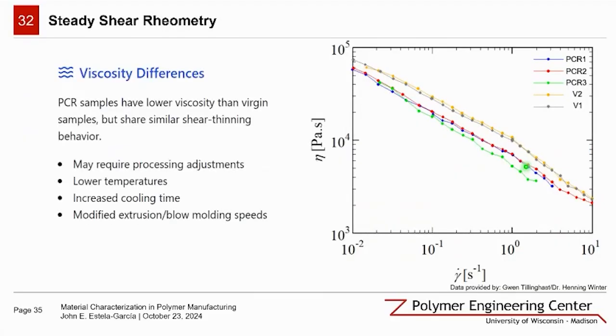Here we're showcasing our steady shear rheometry results, where we notice the lack of a Newtonian plateau in all these samples, which makes it difficult to estimate the zero shear viscosity. What we do observe is clear differences between the PCR here at the bottom and the virgin viscosity, by a small magnitude change. This further validates the results of our HTGPC analysis and the MFI analysis. We notice similar shear thinning behavior for the virgin samples, which is comparable to the shear thinning behavior of PCR1 and PCR2. But PCR3 deviates from the other PCR samples, which has an increased shear thinning sensitivity. So now we're already on the lookout for what's happening with PCR3.